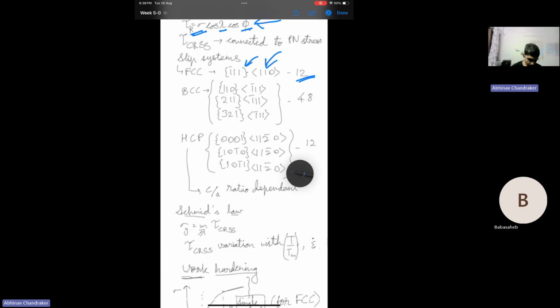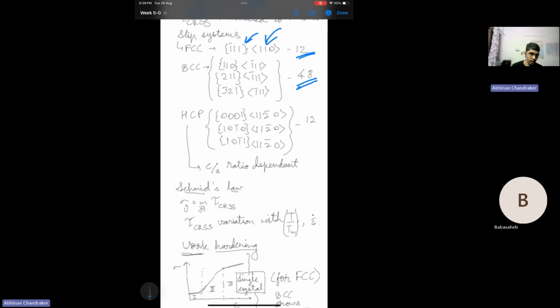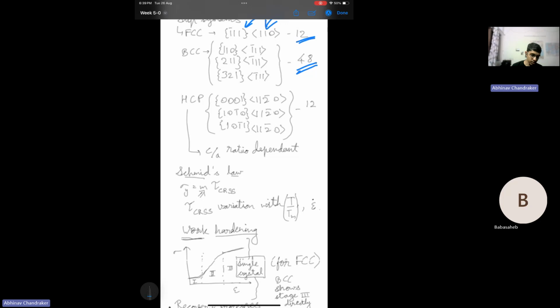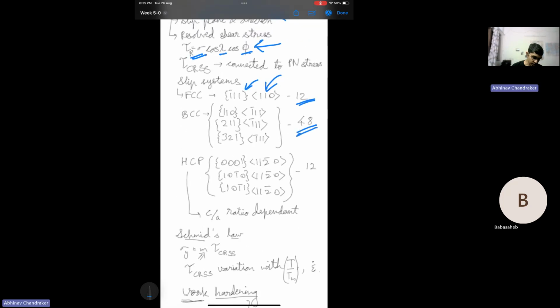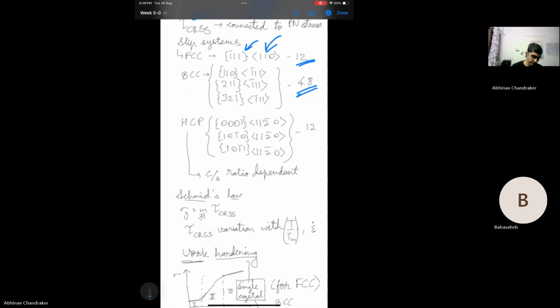In BCC, we do not have as efficient slip systems as we have in FCC. But the number of slip systems on which the dislocation experiences almost comparable stresses is more. So we have 48 slip systems in BCC which have comparable CRSS, or Peierls stress, we can say. CRSS we'll come to later. In HCP we have 12 such slip systems, but they have different Peierls stresses based on the c by a ratio, that is the geometry of the unit cell, because that will also affect the distance between the planes as well as direction.